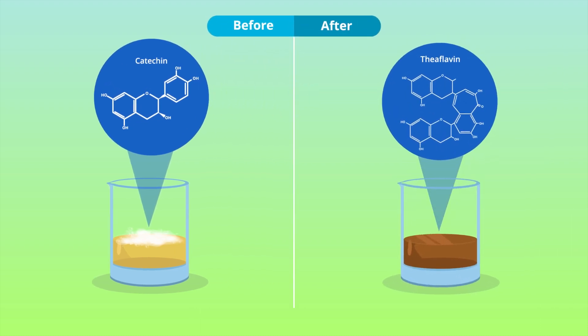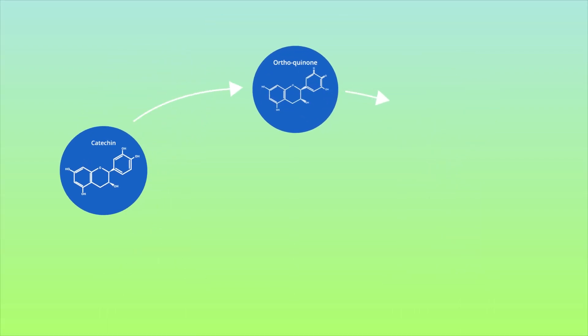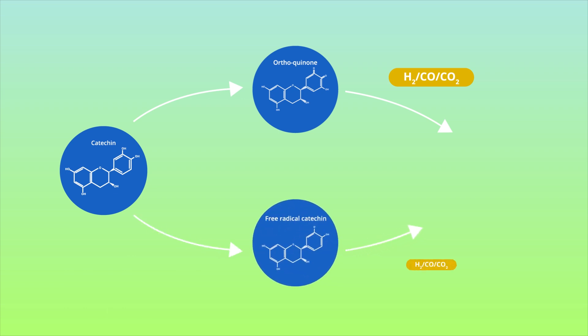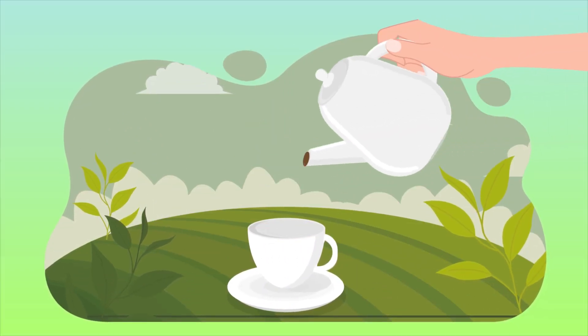This oxidation occurred via either the orthoquinone generated by the catalytic effect of glaze oxides as Lewis acids, or the polymerization of an intermediate free radical catechin.